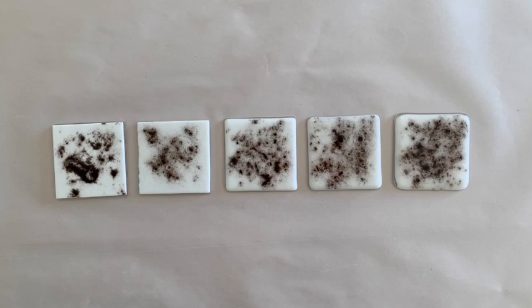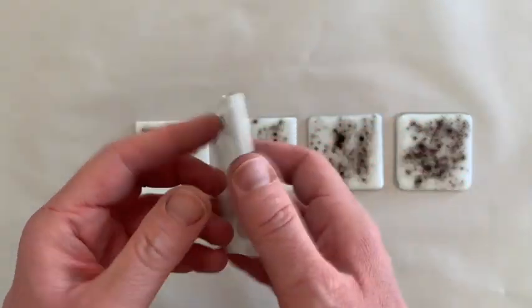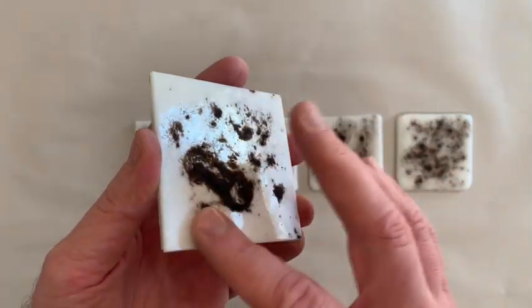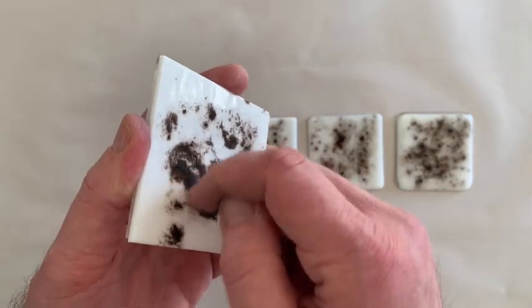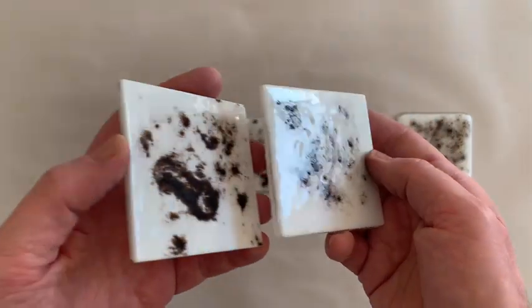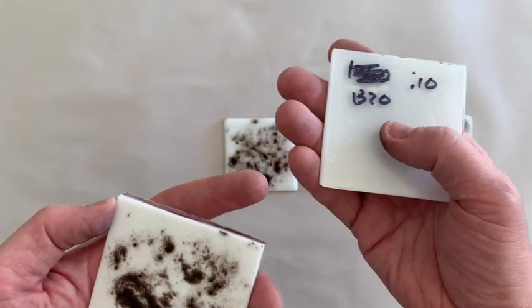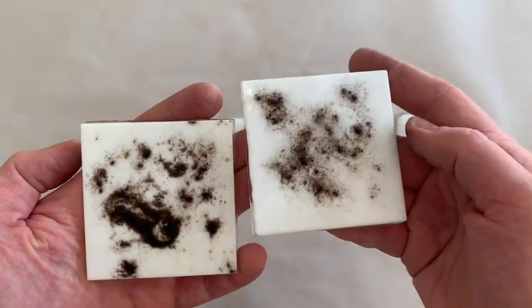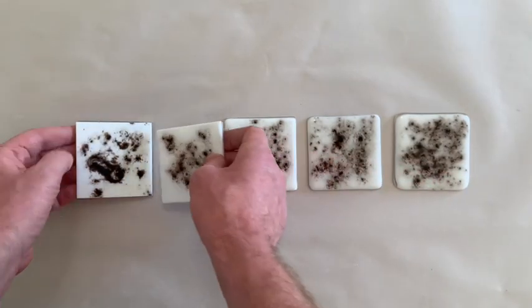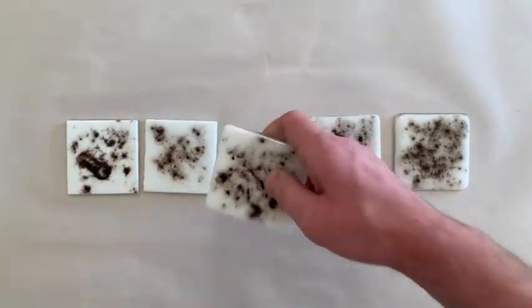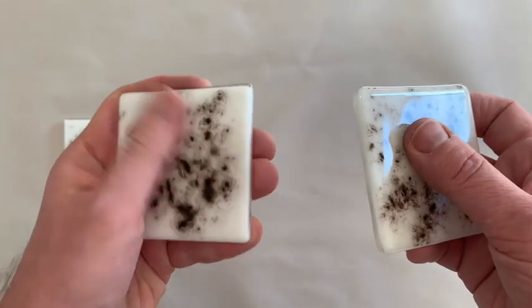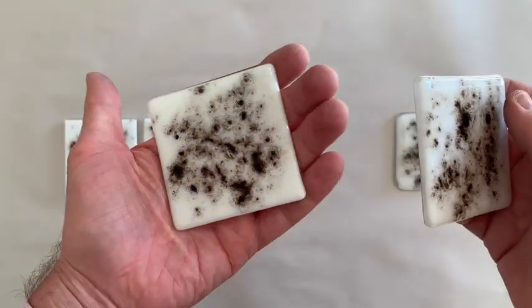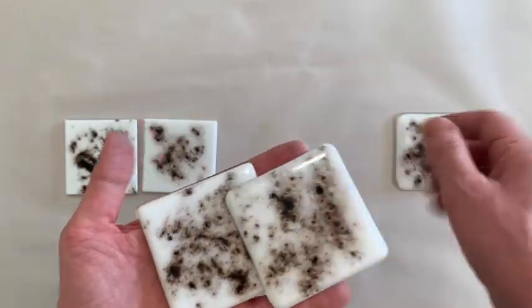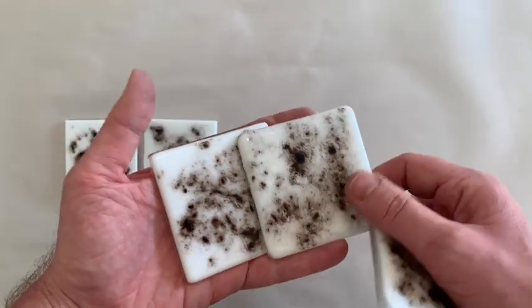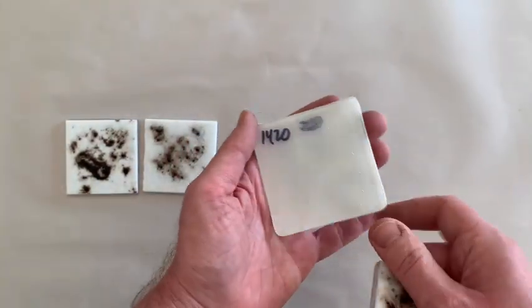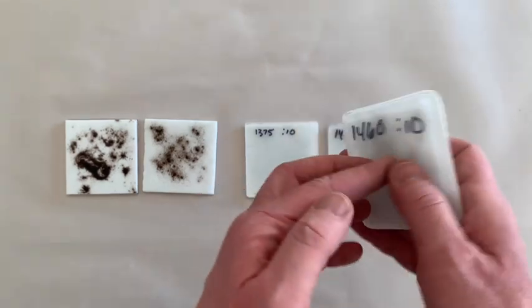Frit powder requires very little heat to fully melt. At 1265 degrees, it is still grainy and sandy on the surface of the white glass. At 1320 degrees Fahrenheit, it is already glossed, but still holds some texture. At 1375 degrees, the frit powder is fully fused into the base glass. Notice the similarities between the samples at 1375, 1420 degrees, and 1460 degrees.